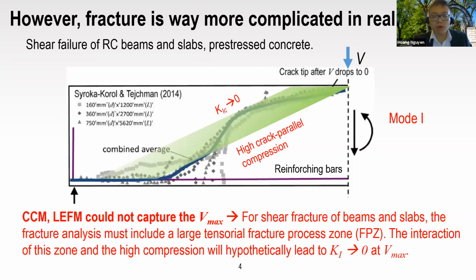So what drew us in this direction is the shear failure of reinforced concrete beams. There were some experiments done on this type of beam and this type of loading configuration. However, when we try to use the cohesive zone model and an LEFM-based type of model where the crack is aligned, we cannot capture the Vmax reflected in the measurements. So when we looked into the problem more carefully, we realized that the shear fracture of beams and slabs must include a larger tensorial fracture process zone rather than an aligned crack.